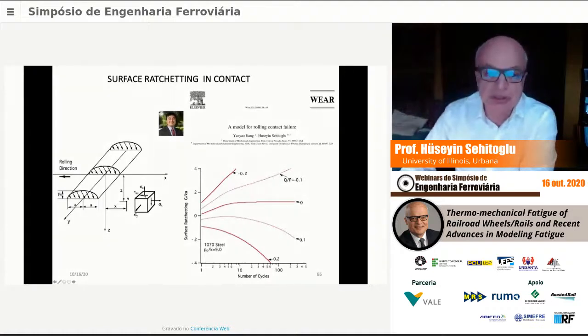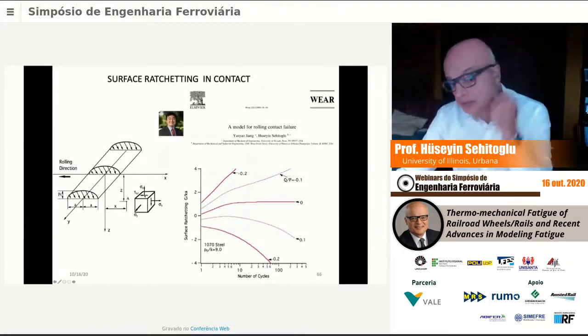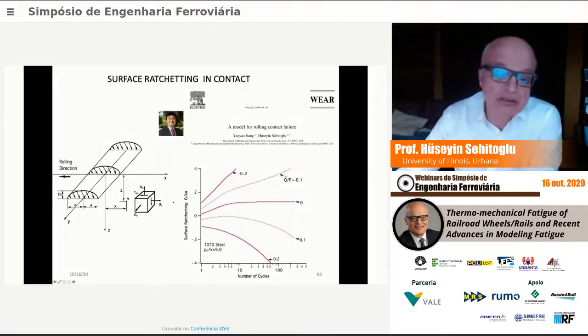So the history is a three-dimensional one. The stresses are three-dimensional. We have tau xz, which is what's called the orthogonal stress. That's important for fatigue. Sigma z is the normal stress. Sigma x and sigma y also exist. And as I point out here, I'm putting the direction of loading here at an angle, so there are shear tractions as well as normal tractions. The student I had who worked on this is Yanyao Jiang. He's a professor at University of Nevada, Reno. That's what his affiliation is now.